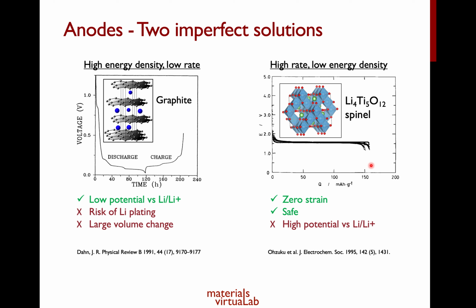And that makes this spinel anode very, very safe, right? Now, the problem with the spinel, of course, is that it has an average voltage of around 1.5 volt versus lithium plus. And what this means is that you lose a lot of energy density if you are using the lithium titanate spinel as the anode.